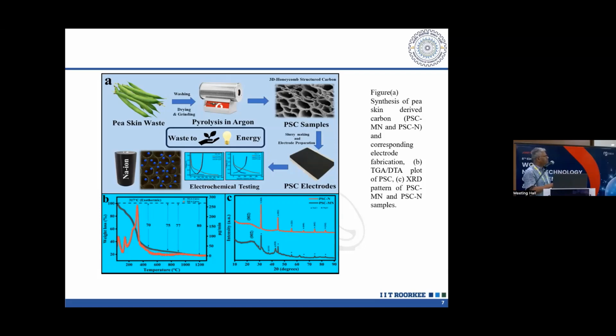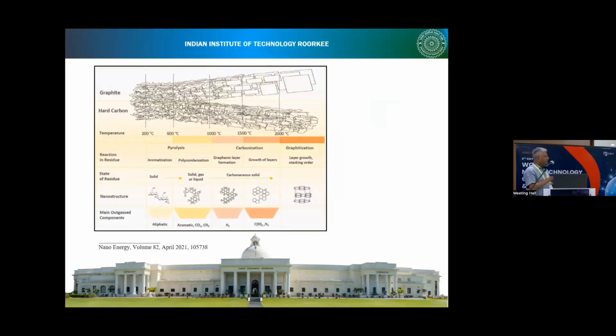Why two different materials are shown: this pea skin material contains, in situ, magnesium oxide as well as sodium chloride. From the source itself it comes. Now our target is to look at whether the material containing sodium chloride and magnesium oxide both will act as a good template making material, how they behave and what the phase differences are. Whereas if it is free from magnesium oxide, what difference comes. So this was one of the targets. So such activity was performed, and this is the pyrolysis process.